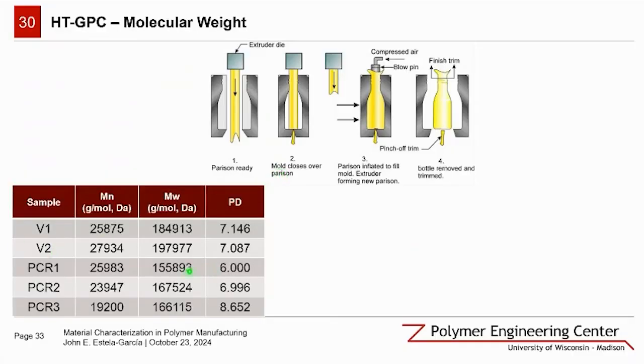Our GPC results reveal key differences between virgin and PCR materials. Virgin samples show higher average molecular weights when compared to the PCR samples, which is expected. What is also interesting is how the polydispersity indices vary. Mostly for all of these, it's stable between 6 and 7, with our third PCR sample showing the broadest distribution. And this variability in PCR can impact processing consistency.